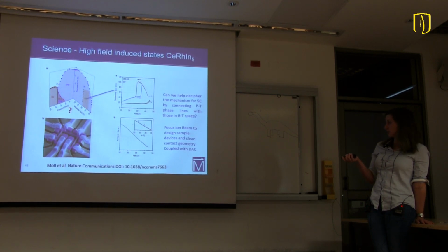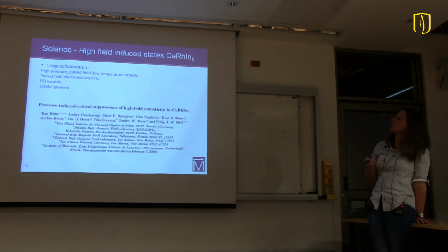So this is what we've tried to do. That was a large collaboration, and we coupled samples that were designed by focused ion beam to have really clear devices and really clear contact geometry. We put those devices on top of a diamond anvil. So, a large collaboration with many different experts.